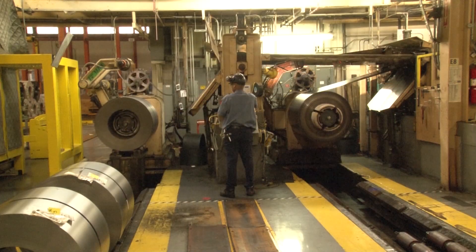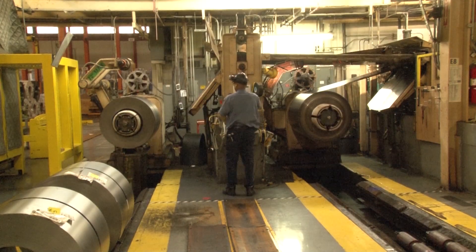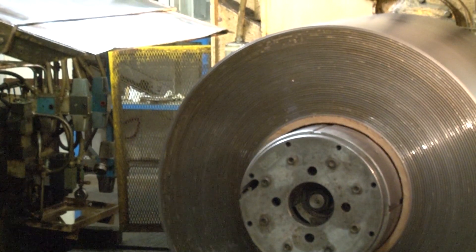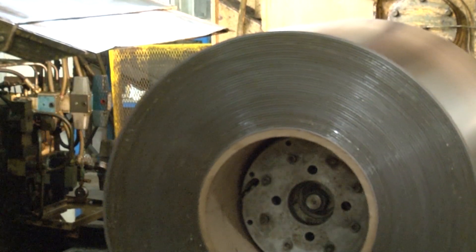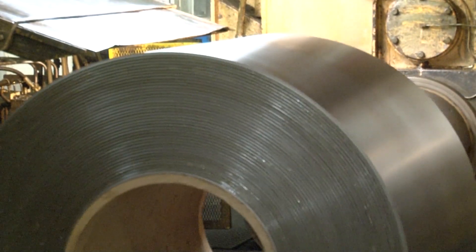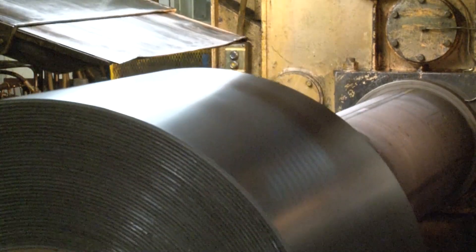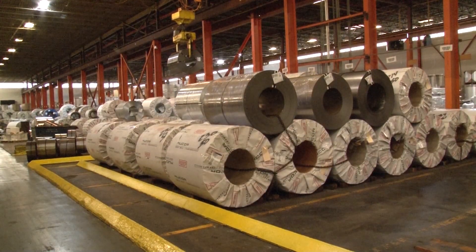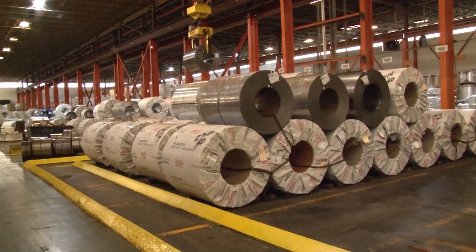This product does have some damping characteristics, but it's more tuned for drop-in weight savings. The other advantage is it'll process through standard e-coat coating systems, it can be spot welded, it's 100% recyclable with the rest of the steel that goes down the scrap chute, and it will process through the standard dies used today. That's what we mean by drop-in — you can just take this smart steel and use it in whatever application you had before.